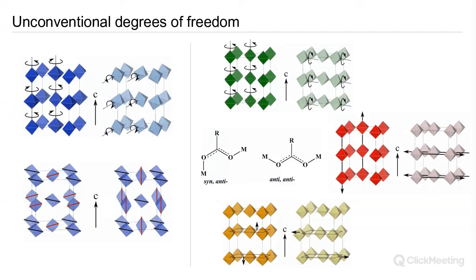And finally, unconventional degrees of freedom. Just to summarize briefly, in inorganic systems, we have corner-shared octahedra sharing a single oxygen atom. So if one octahedron rotates anti-clockwise, then its neighbor must rotate clockwise. Okay, if these octahedra are now connected by a ligand, for example, formate, then we can introduce new structural degrees of freedom into the system. For example, octahedra that rotate in the same fashion, or we can have columns that shift past each other linearly, or we can have planes that shift past each other. So, what is the effect of these different degrees of freedom on the material properties?